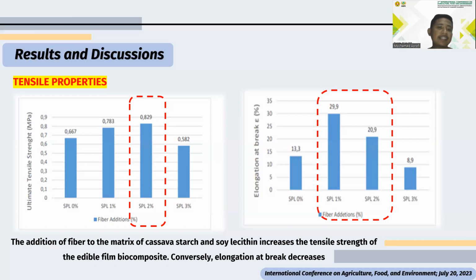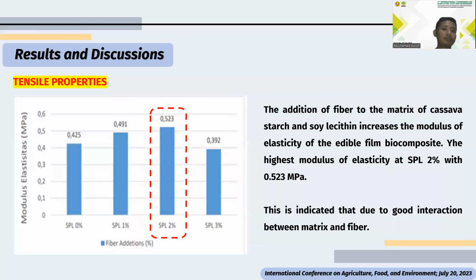And the second one is elongation at break. The elongation at break determines the brittleness, or the elasticity, of the biocomposite film. The addition of the fiber decreases the elongation at break because the addition of fiber increases the brittleness of this biocomposite film. And the last one is modulus of elasticity. The addition of fiber to the matrix of cassava starch and lecithin increases the modulus of elasticity.